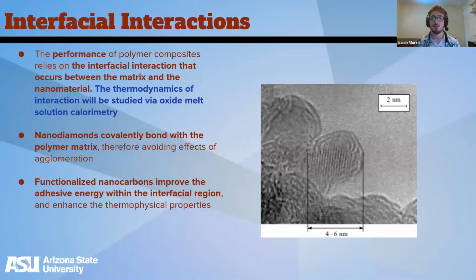But it is important to note the interfacial interaction between the matrix and the nanomaterial, as the performance of polymer composites relies on such. And the thermodynamics of this interaction will be studied via oxide melt solution calorimetry alongside Alexandra Navrotsky and her calorimetry team here at ASU. Now, it is important to know that these nanodiamonds are covalently bonded with the polymer matrix. They are not additives, they are not fillers. They become one with the system. This becomes a multi-structure system, if you will.